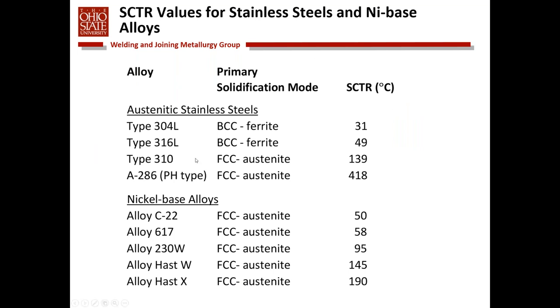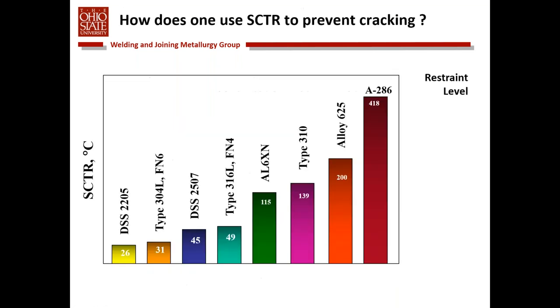So if we look at SCTR data for a variety of materials, austenitic stainless steels, nickel-based alloys, it can show quite a variation. In type 304L, which solidifies as ferrite, that value is fairly low. In stainless steels that solidify as austenite, the SCTR value is much higher. There's a range of values in nickel-based alloys. These all solidify as austenite, but have different alloying elements that make them more or less susceptible to solidification cracking. So this value of SCTR becomes a real-world measure of cracking susceptibility. And frankly, these values match up pretty well to what is experienced in actual practice.